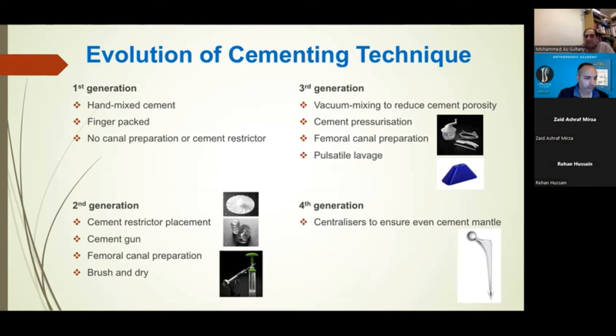Over time, the second generation had the introduction of the cement restrictor, like the Hardinge restrictor here. You've got various different types on the market, and some surgeons actually use a bone block rather than any of these materials. You've got a cement gun as well to help you pressurize the cement in the canal. So with a restrictor you're able to pressurize and make sure the cement interdigitates into the cancellous bone so that you're getting a great anchorage. But before that, you want to brush and dry the canal so you don't get any blood mixing in at the interface and delaminating.